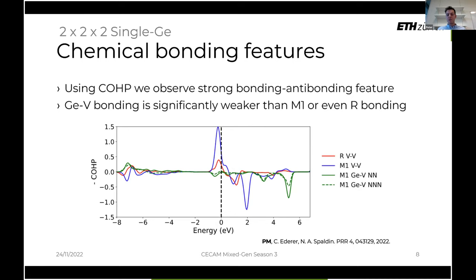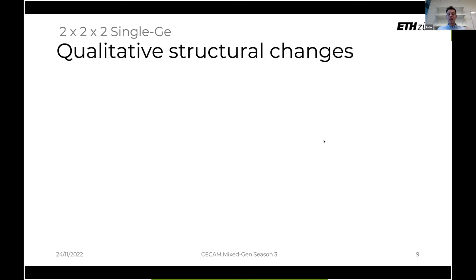Especially around the Fermi level, we see almost no bonding behavior between germaniums and vanadiums, with only some interaction occurring in this energy range down here and this energy range up here. And these features are much weaker even than the rutile phase, which we know does not host a dimer, so it does not host a bond. So with these things in mind, we can think about the germanium doping as some sort of added structural effect in our system. We have our vanadium system, we add the germanium, and we have some structural disorder created. And indeed, we observe already in this smaller cell a qualitative structural change.